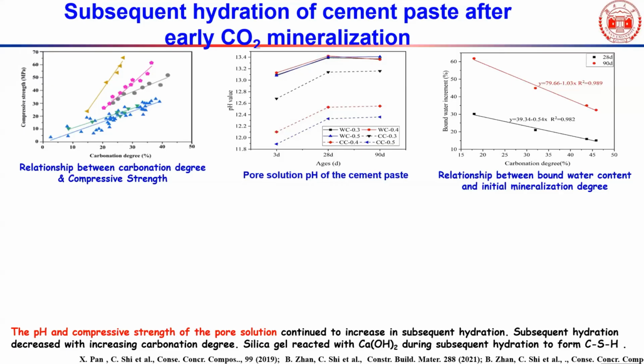Well, another thing is, people start to be concerned about how carbon mineralization affects the alkalinity of the product, or the steel corrosion, right? This first big figure shows the relationship between compressive strength and the carbonation degree. Then we measured the pore solution of the carbon mineralized product after it was hydrated. You can see in the middle figure, without carbon mineralization, the pH is over 13. But if we carbon mineralize the sample for several hours at the beginning and then hydrate it, the pH is above 11.8.